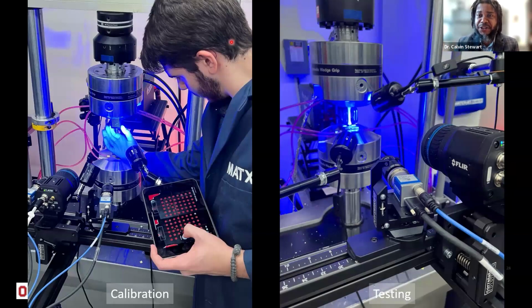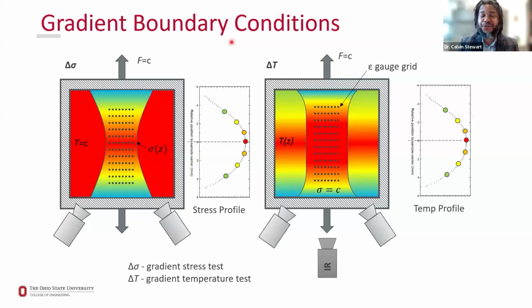Now, as we overcome all of those challenges in this new technology, it enables us to get some very interesting information. One duo of tests that we've been developing, we call the gradient boundary condition tests. These are tests that, instead of following ASTM standards and having a uniform sample for one value of constant stress, or finely tuning our temperature to have a set constant temperature in the vicinity of the sample, instead, we use what the real world gives us, stress gradients and gradients of temperature. That's the real world. And if we can map those gradients, if we can design a sample with a bell shape where we can calculate what the stress is as a function of area, and we can capture the strain along those different values of stress, well, guess what? We just developed a test where we can get hundreds of individual conventional tests from a single sample. Make one sample, get 100 test results, right?